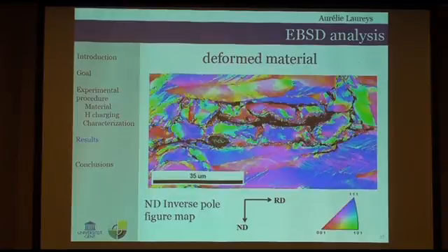If we then look at a more evolved crack, so already one that has been branching and reconnecting again, we see the overall matrix is quite deformed because we're working on deformed material, but we see that the misorientations around the crack are even higher. So this again implicates the internal pressure theory, where the pressure pushes and induces strain into the material that is surrounding the crack.